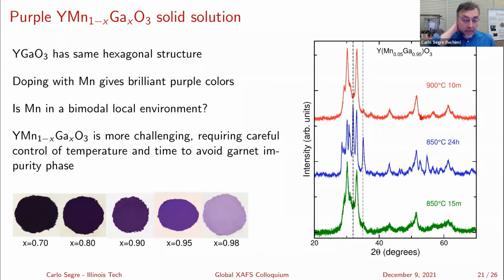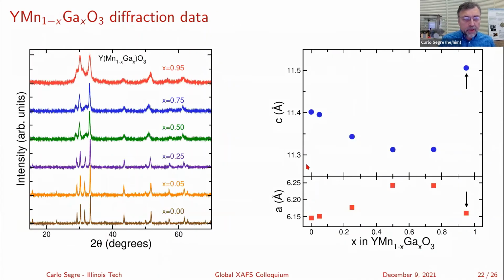900 at 10 minutes and quick quenching, it's a little bit better, but the peaks are very broad. It's not well crystallized. And so there are very big issues with making a material with a very low quantity of manganese in this. But he did his best. It's just a little bit tricky. We did it by sol gel to try to reduce the amount of time. So we were able to make it up to about 0.5, maybe 0.75. But you can see that the c-axis is not changing here. So I think we've reached a point, and over here is certainly not working well.